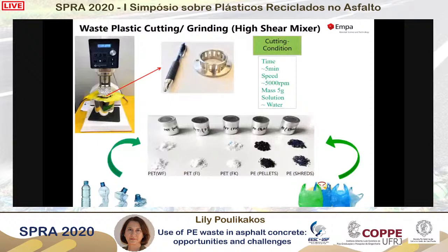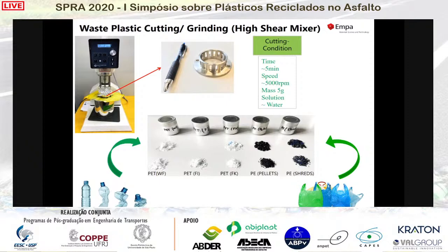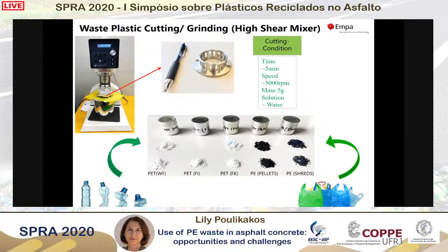So here, in addition to PE shreds and PE pellets, we have also looked at the PET coming from plastic bottles, also supplied by a Swiss waste management company here in Switzerland. What we found out very soon is that the way we receive them from the plants, we cannot blend them into our binder. So we needed to shred them further, and the last row shows these materials after they were shredded.